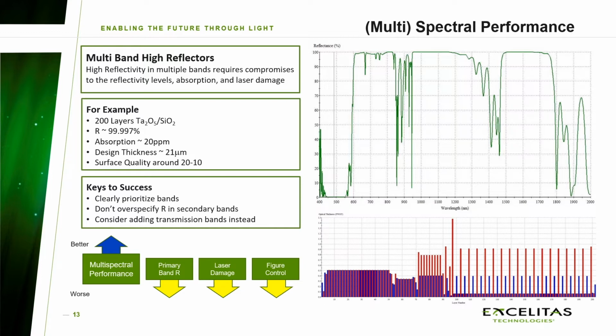But as we increase the multispectral performance, we're going to compromise on the rest. We're going to compromise a little bit on the primary band reflectance. We're going to compromise a little bit on laser damage. Figure control is going to be a challenge because these thick coatings carry a lot of stress, and so now we've got to pay a lot of attention to how we're mitigating or compensating for that stress in one way or another.